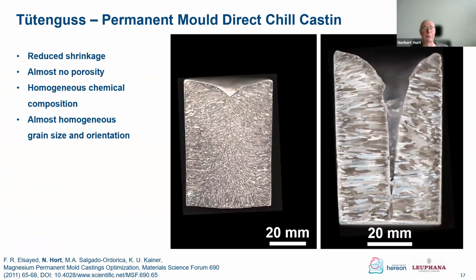And the advantage of that process is pretty simple. On the right-hand side, you see a standard billet simply cooled in the mold by air. You see drastic shrinkage. You see large elongated grains, and this you can completely avoid by this kind of process. So select your processes accordingly. And with this process, you have almost no porosity. It's homogeneous from a chemical point of view. It's almost homogeneous with the grain size and the orientation of the grains.